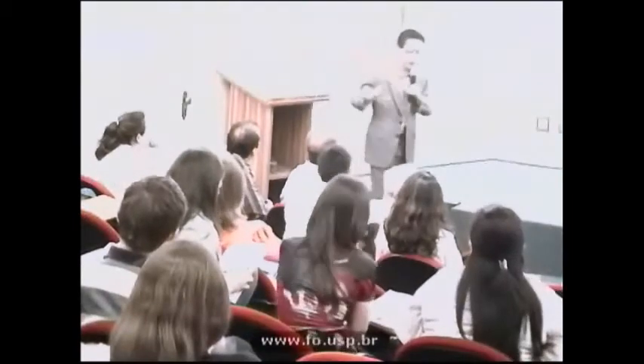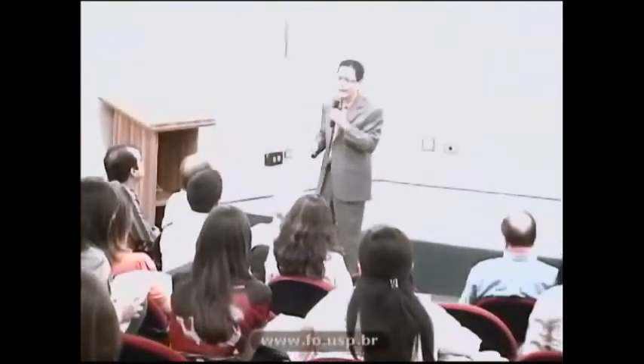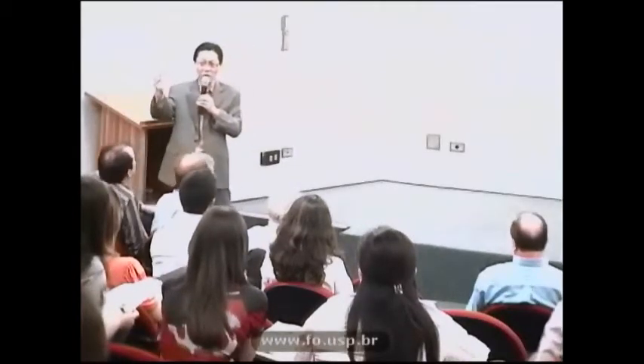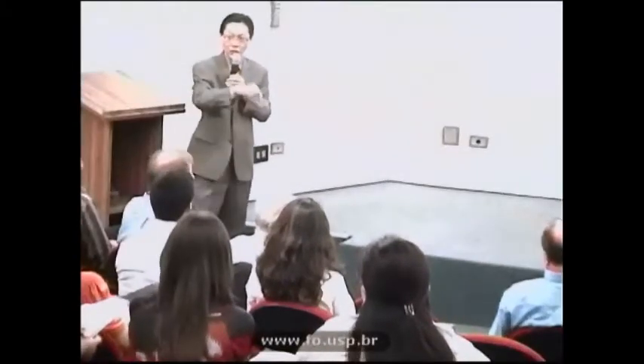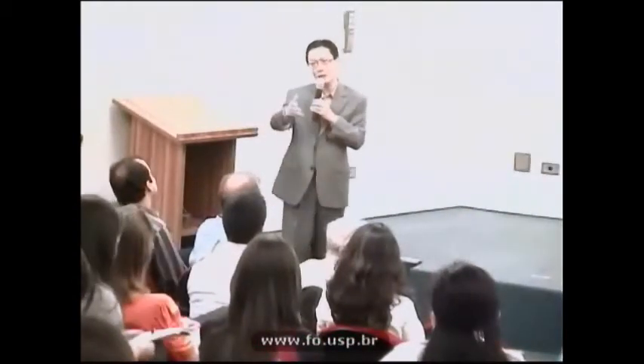We use a glass ceramic infiltration technique, and the key is you have to come up with a glass composition whose coefficient of thermal expansion matches your target materials, whether zirconia or alumina, because otherwise you introduce thermal stresses into the system. So you can do it two ways. One is you can lightly sinter your material and infiltrate glass into it. But you can also almost densify the material and you're still able to infiltrate it.